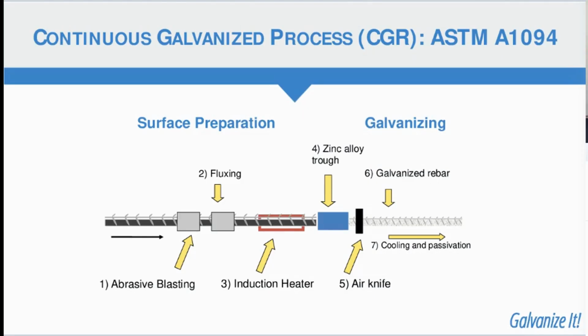Alternatively, the continuous galvanizing process, or CGR, under ASTM A1094. This involves rebars that are placed in individual lanes, then blasted clean, fluxed, and then they're heated, and then they're actually sent through a trough of zinc and then wiped of any excess zinc by an air knife. The metallurgical reaction between the rebar and the molten zinc is similar to the batch process. It just doesn't take place as long because of the relatively high speed with which the rebar passes through the zinc alloy trough. So this results in a mostly 100% zinc galvanized coating consisting of a very small percentage of alloy layers.